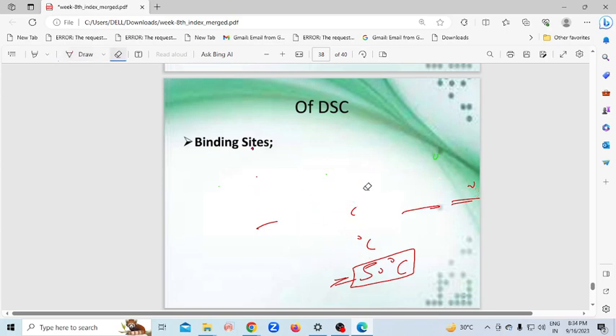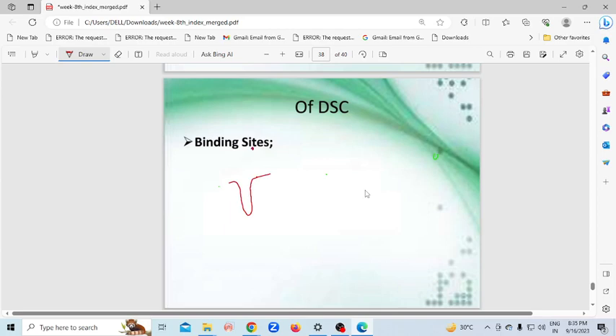Okay, then some more concepts. We have already discussed there is a large well-defined endotherm in DTA, which is due to pure crystal melting, liquid crystal, dehydrate, hydrate loss, meaning water loss, and stress relaxation. These are the phenomena where you will get a sharp endotherm, because all these things require energy. Then a shallow endotherm is from moisture loss, because moisture loss needs energy for a longer time, that's why you get a shallow broad endotherm. Then also residual solvent and monomer losses.